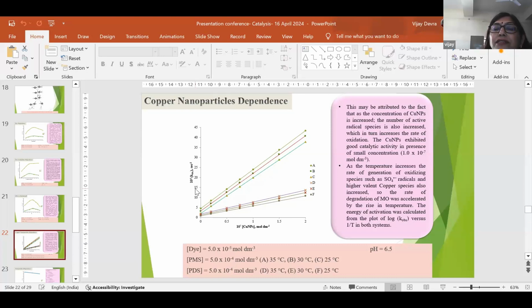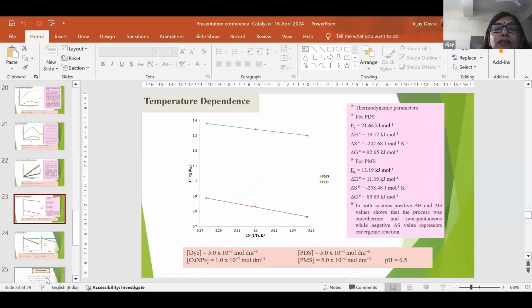And here we also calculate the activation energy in both systems by plotting the graph between log K versus 1/T. The activation energy is 21.64 in the case of peroxodisulfate, and in the case of peroxomonosulfate, 13.19 kilojoule per mole.